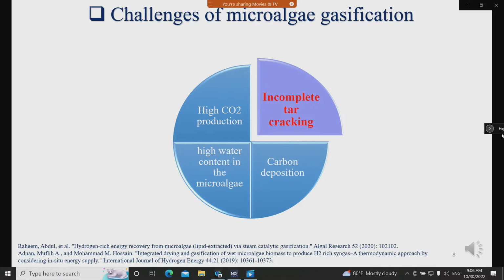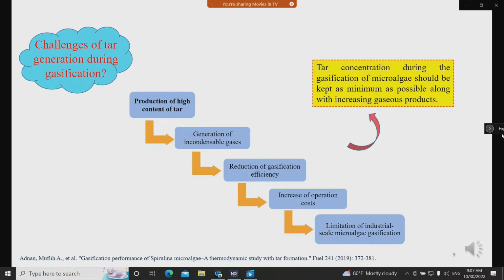Importantly, these problems can be addressed using catalytic gasification with novel catalysts, especially perovskite-type oxide nickel catalysts, which will be explained. As already mentioned, among all challenges of gasifying biomass, for example microalgae, formation of high tar content has been known as the main problem for scaling up gasification systems. A higher tar yield reduces the gasification efficiency and causes serious challenges such as gasification reactor pipeline obstruction and increased operation and maintenance costs.